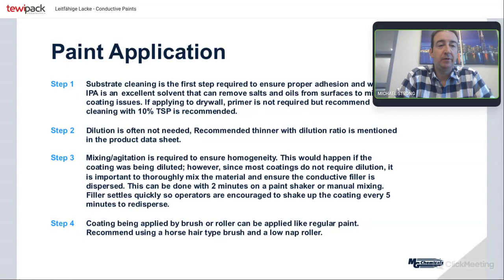So now moving forward, we're looking now at paint application. So if any of you have painted in the past, this isn't a big shock to you. For the most part, we want to make sure to start that our surface is clean. Surfaces that are not clean, we run the risk of having the coating not wet out and spread over the surface area. And that's very problematic with a conductive coating because, again, we want to make sure the entire surface is coated so we don't have any holes in our Faraday cage. And so the easiest way to do that is with IPA or isopropyl alcohol. It's a great durable workhorse solvent, removes a lot of salts, a lot of oils, fingerprints, cutting fluids, stuff like that. So we give it a wipe down, make sure everything is clean.